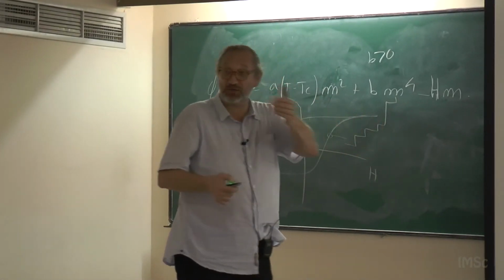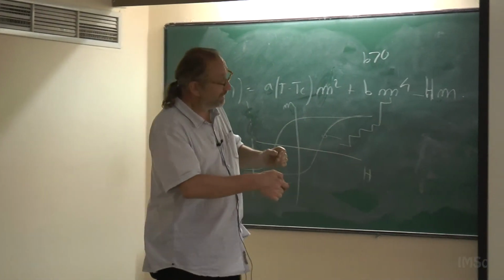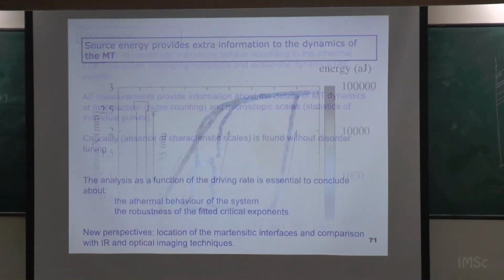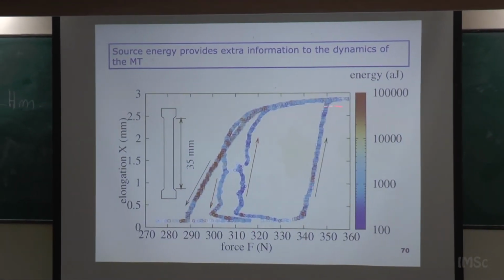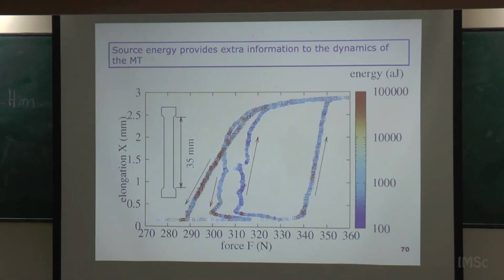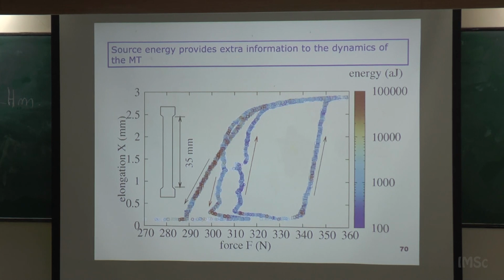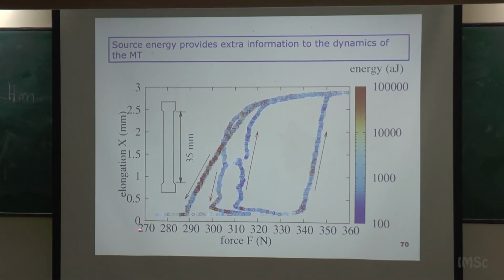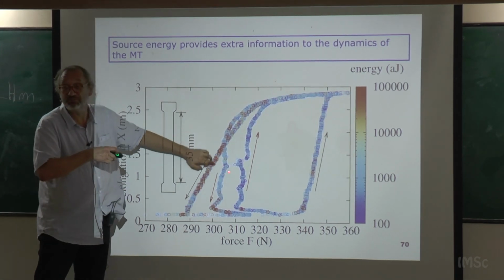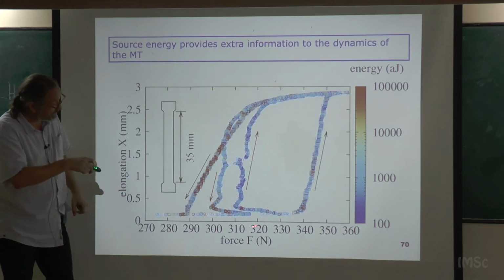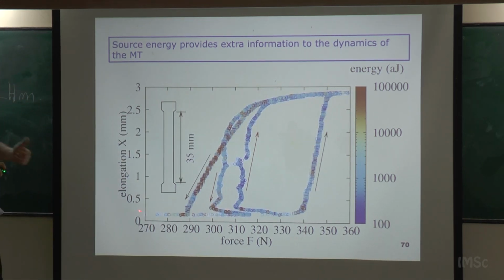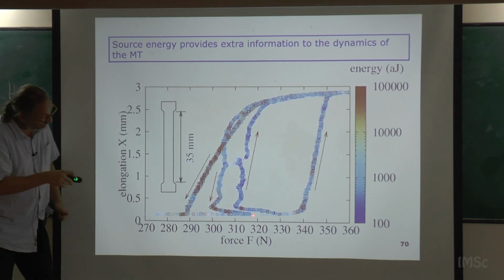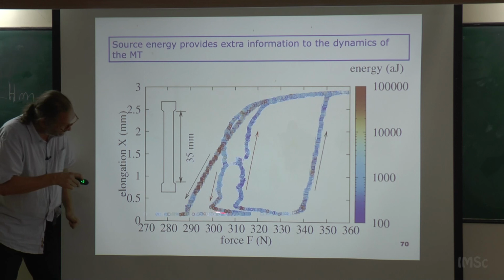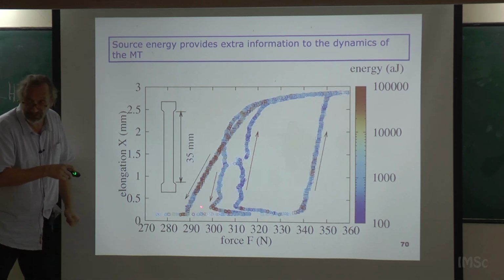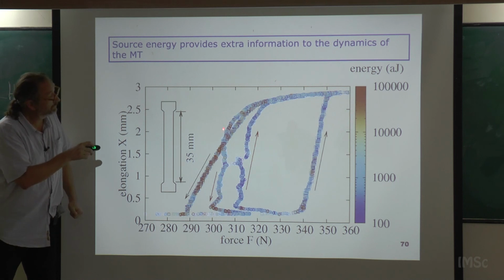And then you can find, for every event, the energy at the source, and you can plot your hysteresis curves. These are the hysteresis loops. Okay? But when you detect an event, you put a symbol with a color that is proportional to the energy of that event. So, for instance, here you discover that when you go back, you have more acoustic emission with larger energy in this part. Okay? And vice versa. For instance, when you do the driving by the speed, you have the yield point, and here is where you have most of the large avalanches, the red stuff. And then you have the plateau, okay?